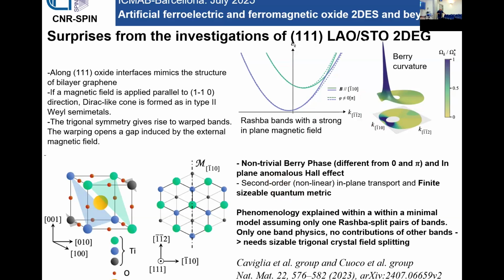The Berry phase really determines many properties of this two-dimensional electron system. A non-trivial Berry phase is different from zero, which is what you get in disordered metals without spin-orbit coupling, and different from pi, which is essentially the Berry phase of a two-dimensional electron gas in the presence of spin-orbit coupling, which is trivial. In principle, with a very strong in-plane magnetic field, you get a non-trivial Berry phase, and one of the consequences is the presence of an in-plane anomalous Hall effect. Another is the second-order nonlinear in-plane transport due to the quantum metric, which is a very exotic property of condensed matter systems.